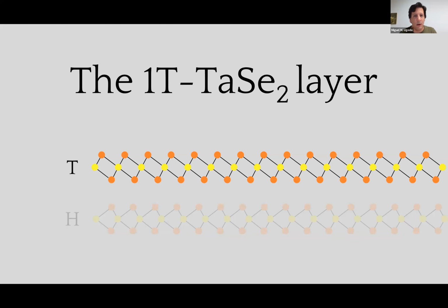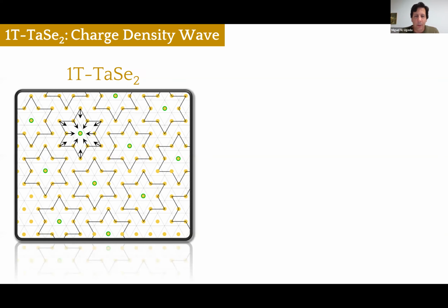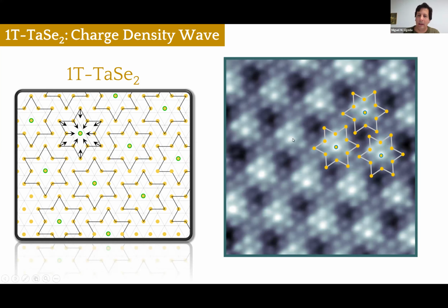Yeah, as I said, let me give you some words about the 1T phase. First of all, let me explain why this polytype of tantalum diselenide, which applies as well to niobium sulfides and other types of 1T phases in TMD materials, hosts isolated magnetic moments. The reason is that these materials at low temperatures undergo a charge density wave, which is called the Star of David for obvious reasons. Below this critical temperature, the material rearranges in a superlattice like this, where there is a central atom, and the 12 surrounding tantalum atoms undergo an elastic deformation going towards the central atom like this. This is something that can be easily detected in STM as well. You can see here the central atom and the 12 surrounding atoms around it.